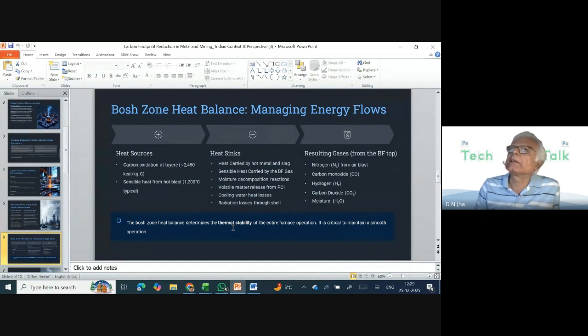Apart from that, the burden itself will carry some moisture. For example, sinter may not carry a lot of moisture, but sized ore certainly will have moisture. Because of the heat, it evaporates all the moisture that is carried by the burden. Apart from that, if the coke is not dried coke, then the coke will also have some moisture varying between 4% to 8%, which is a substantial amount of moisture. That moisture also, because of the evaporation happening at the top quartile, the top one-fourth of the height of the blast furnace, gets mixed in the top gas.